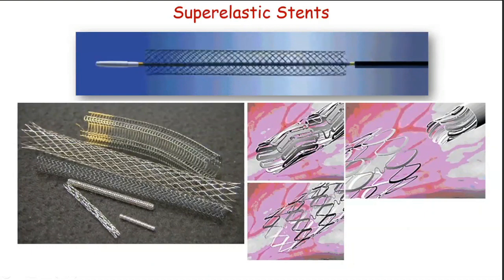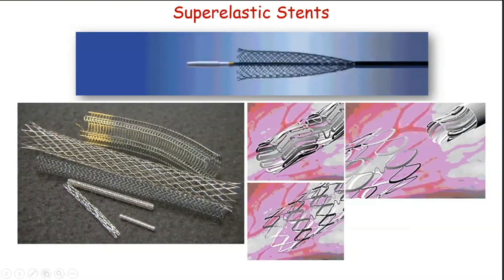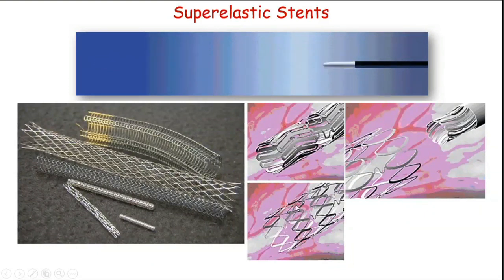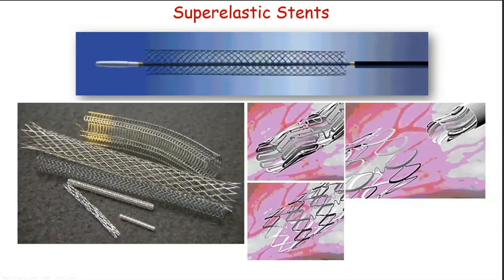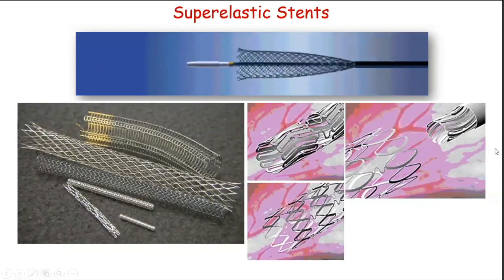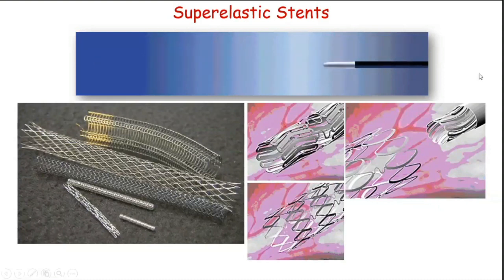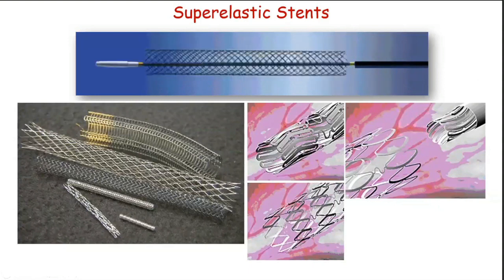So a tube of such a kind of nickel titanium, what they do is laser cut it, and it can be about as thin as about 25 to 50 microns. So it's very pliable. It's almost indestructible at these thicknesses, and they also make it like a drill, so it can accommodate all the deformation. And when you put it into a cannula or a catheter or something like that, you can push it in, take it to the location where you need to deploy it, and as it comes out, it'll unfurl to its original shape.